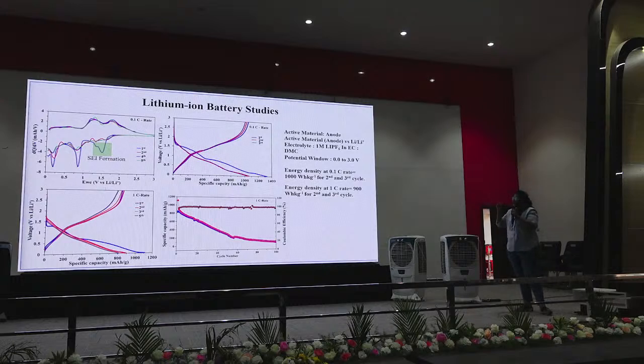In the first cycle you see 3 reduction peaks down. These peaks are due to the SEI formation. When you see the second, fourth and fifth cycles, they do not have that peak. So this confirms that something is happening in the first cycle, which is the SEI formation in the battery discharge cycle. This is the graph for the 0.1 C rate.